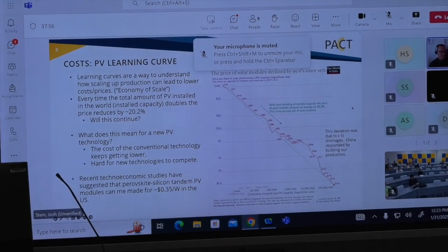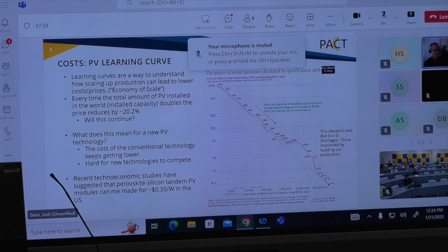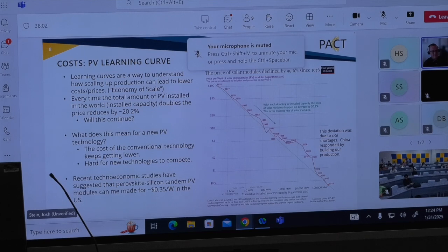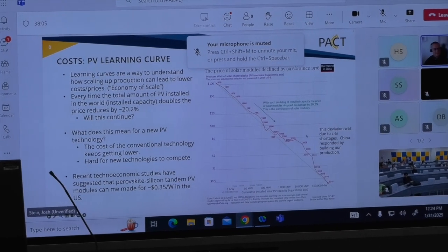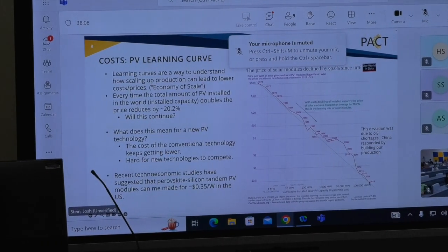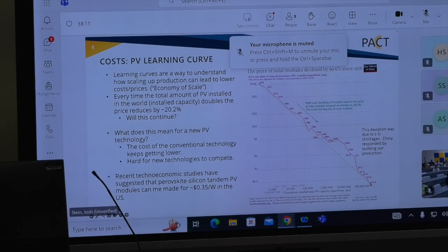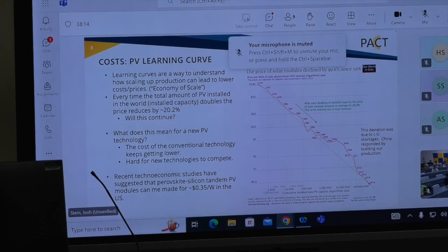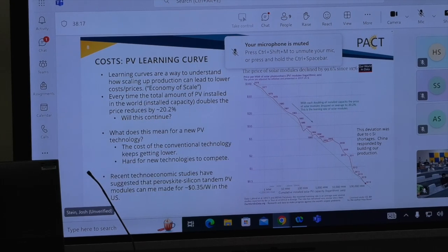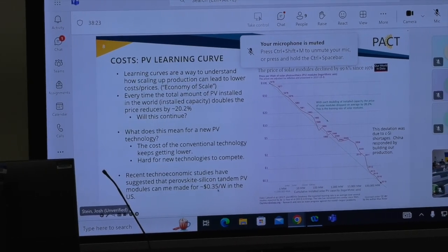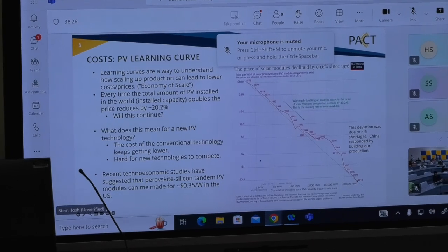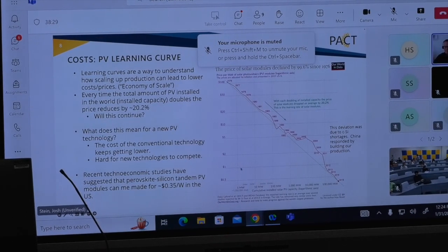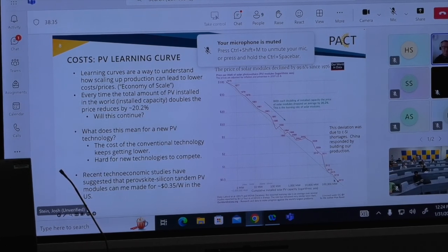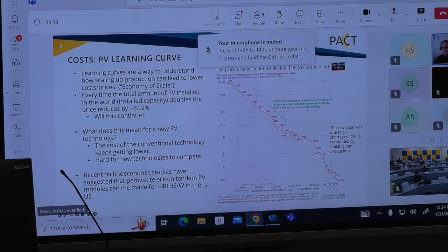So some of the recent techno-economic studies have suggested that perovskite silicon tandems could be made for about 35 cents a watt in the US. But if you look at 2019, we're almost at that with crystalline silicon. And so that's a challenge for perovskites, that crystalline silicon modules keep getting cheaper. And I think some of these estimates are not low enough to actually be cheaper than even this very expensive way of making these materials, largely because they're made mostly in China, where the cost of manufacturing is a lot lower.